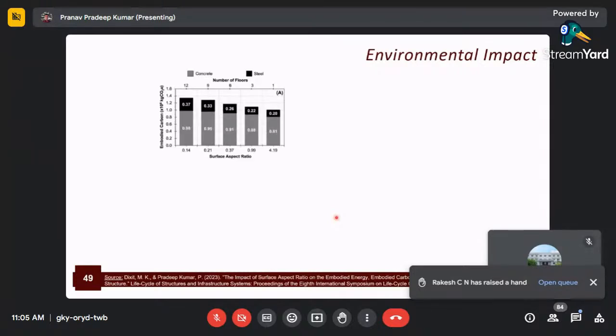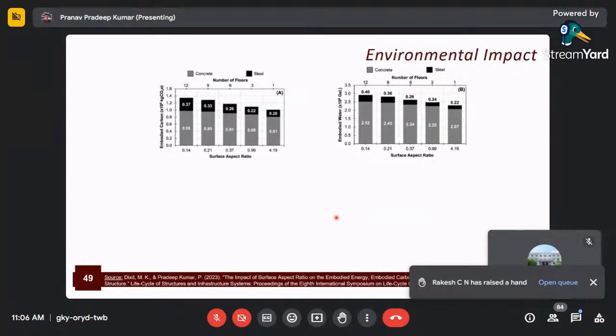And from a carbon, energy, water perspective, I would say that the contribution of the embodied carbon of concrete and steel decreases with the increase in surface aspect ratio or with decrease in number of floors. And also the contribution of embodied water of steel decreases with the increase in the surface aspect ratio. And the variation is relatively lower as compared to the embodied carbon. So you can see that there is still a trade-off, even at a building level, between embodied energy or carbon and embodied water.